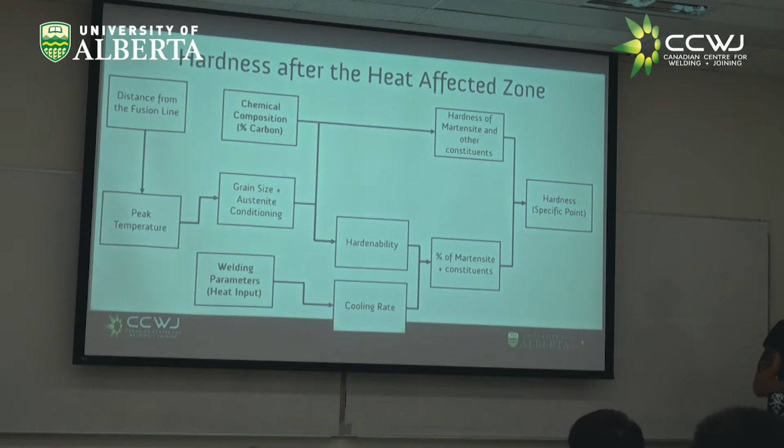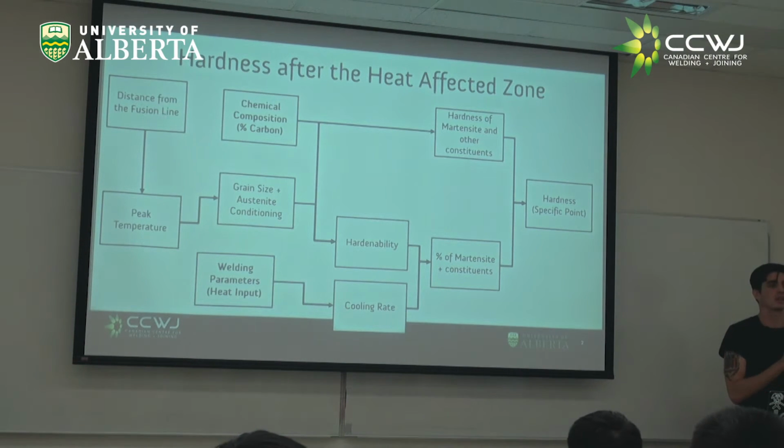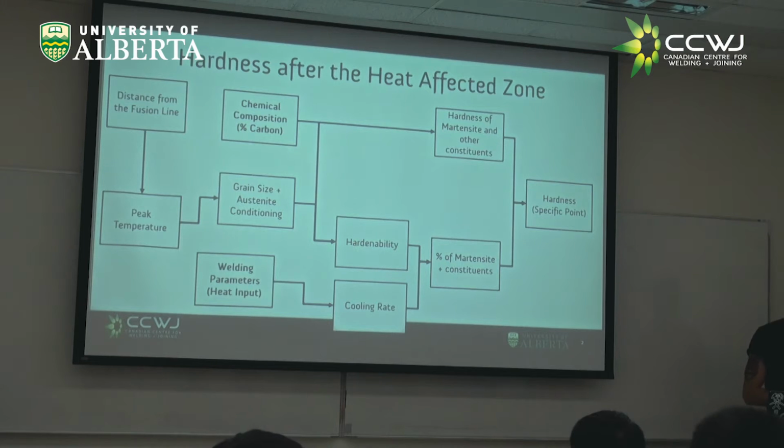It has to do with how the austenite is at high temperatures. Because hardenability means that your austenite is going to transform to martensite, right? So the austenite characteristics are the ones that are going to define how hardenable your material is. So what is the main variable you have in austenite? Chemical composition.